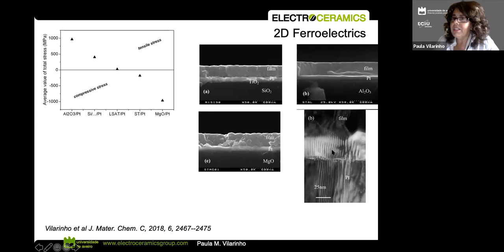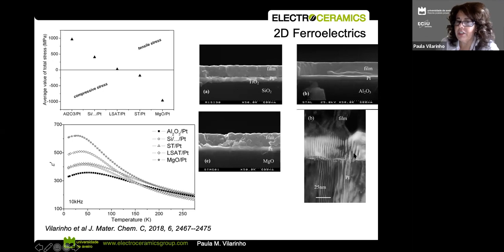So what good properties can I get from here? If you see here, when I do this on magnesium oxide, this is obviously a different microstructure. We have a lot of these dislocations. It looks like this film is quite stressed. It's compressive stressed. Let's see what is happening in terms of the dielectric permittivity. And if you look here, it's very interesting. It's exactly the film that contains, in this case, more compressive stress, with a lot of these dislocations, that has the highest permittivity. So by simply changing the substrate, I was able to increase drastically the electrical response of my material. I would not be able to do this with a bulk material.